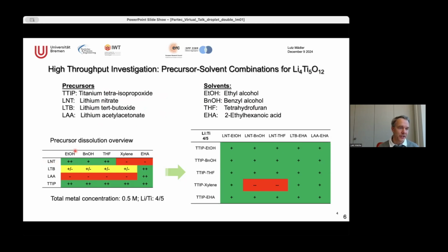As you can see here, these are the solvents: ethanol, benzyl alcohol, tetrahydrofuran, xylene, ethylhexanoic acid. So these two here are one of our favorites because they have good combustion enthalpy, but they are not always dissolving some of these precursors. So these are the precursors here: lithium nitrate, lithium tert-butoxide, lithium acetylacetonate, and TTIP, the titanium precursor. So only the green ones you can actually use, and then you leave them.